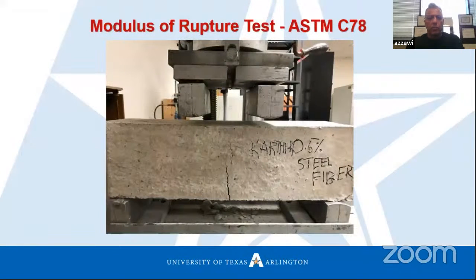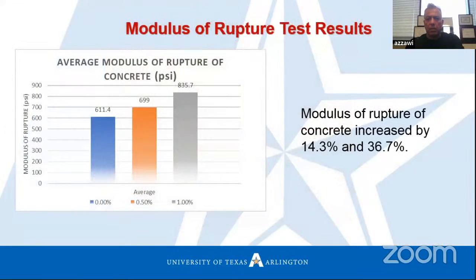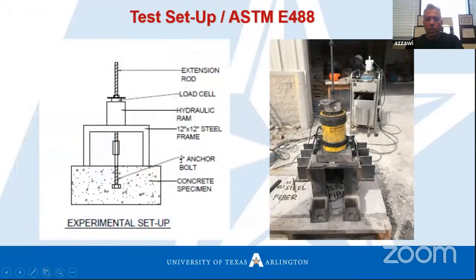And also we test the modulus of rupture based on ASTM C78, and these are the results. Also, we find there's a remarkable improvement in the modulus of rupture for these specimens.